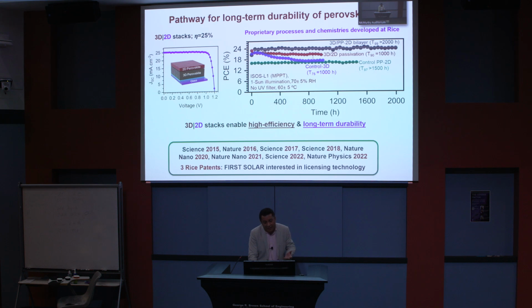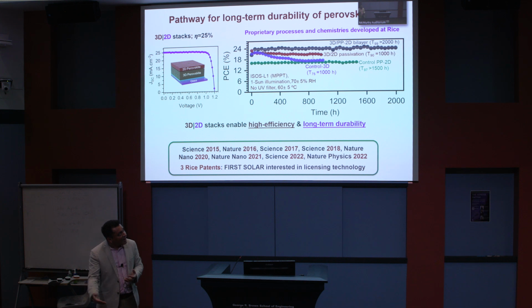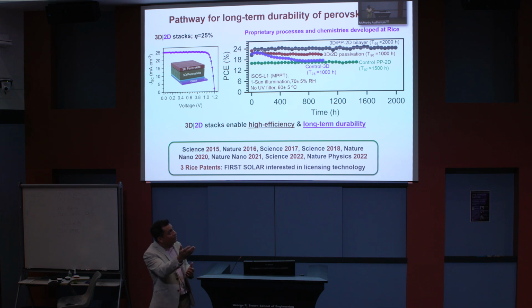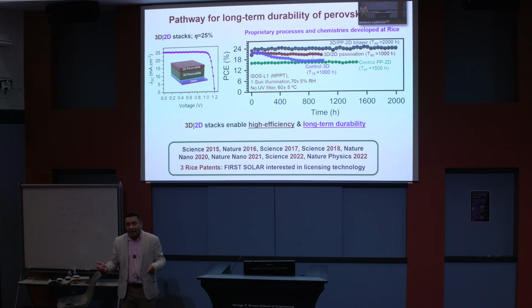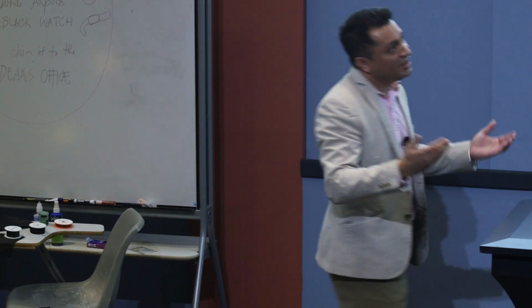And what my lab has been working on is to address this issue of stability. And so I'm very happy to share that we have some really exciting breakthroughs where we can now combine a few different perovskites and create a photovoltaic device which has 25% efficiency, but then get stability, which is the curve on the right. I'm showing you the power conversion efficiency as a function of time. This is tested in the lab under one sun illumination, under operating conditions, and you can see that we barely get any degradation. And so this is a huge breakthrough in the field, and we think that this is really the pathway for commercializing the solution-based technology, which has really been the dream of many researchers for decades.